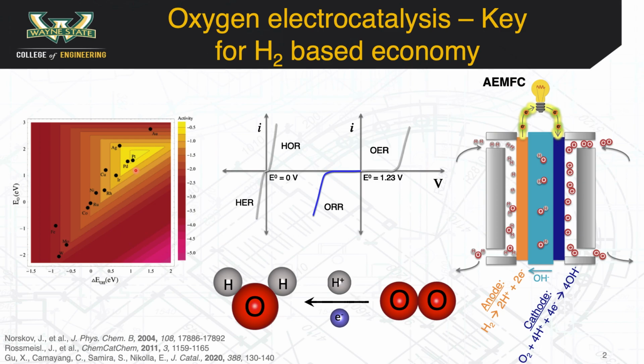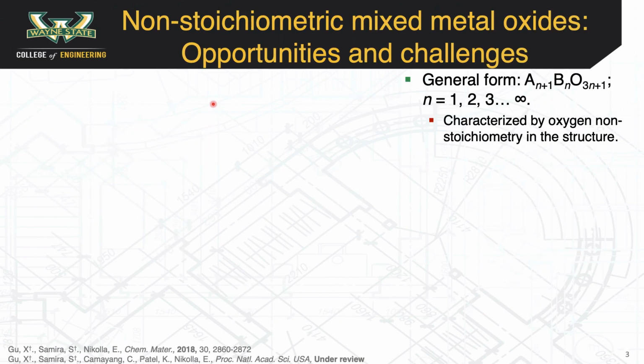In order for widespread implementation of these technologies, there's a need to move beyond these precious metal based catalysts to something that is cost effective. One particular class of materials that fits this bill is that of non-stoichiometric mixed metal oxides of the general form A(n+1)B(n)O(3n+1). These oxides are characterized by oxygen non-stoichiometry in the structure. The A and the B sites are generally metals. N can take values anywhere between n equal to 1 all the way through n equal to infinity.